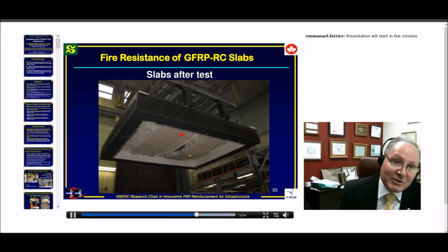And now what we are doing is, tomorrow we'll be casting the next 2 slabs, and the test will be repeated exactly the same as I showed you, but with a concrete cover of only 40 millimeter. And I can tell you, if we can prove moving from 60 to 40 millimeter, this makes FRP for parking garages extremely competitive, because for steel, they are specifying 70 millimeter, for corrosion issues and many other issues.